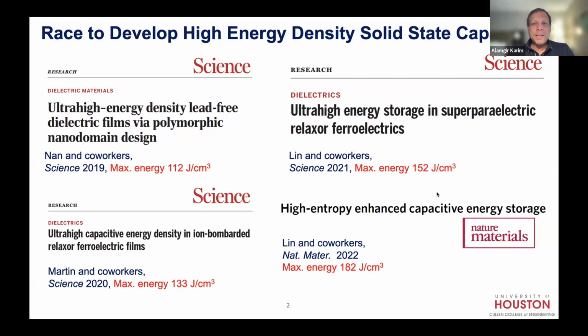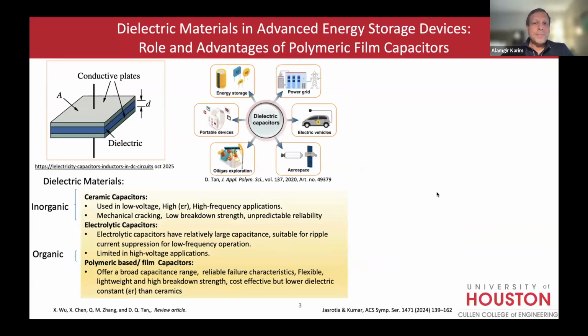But in these examples, mostly use ferroelectrics, and ferroelectrics have a significant disadvantage in that the energy loss is high, because you have domains of aligned dipoles and so on, and moving domains around with grain boundaries, friction and all that is very wasteful in terms of energy. So the energy loss is very high, and these would be very hard to make commercial, for long-term storage and things like that.